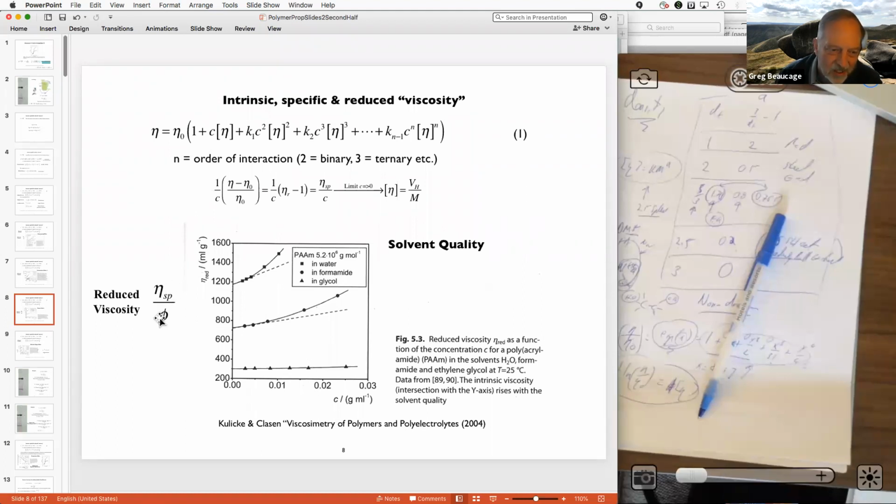So you have to be really careful, because it's easy to interpret the intrinsic viscosity as a thermodynamic number, but it isn't, right? Because it's a dynamic number. So it's going to depend on the shear rate. It's going to depend on how well the water kind of sticks under that condition of the shear rate. That'll change the size and the density of the object, the apparent density. So the chains could all be the same size. It could just be draining differently when it goes to different solvents.